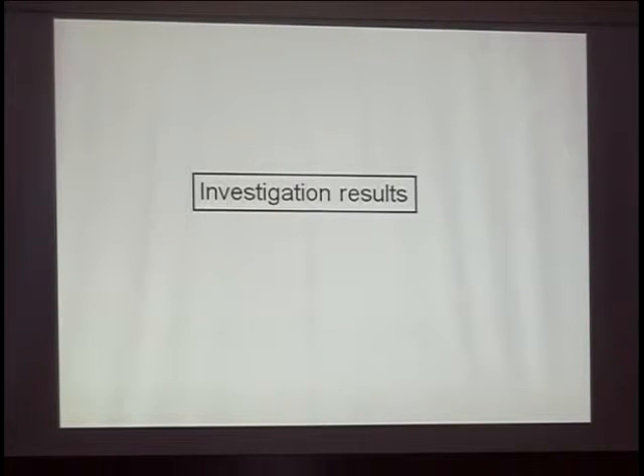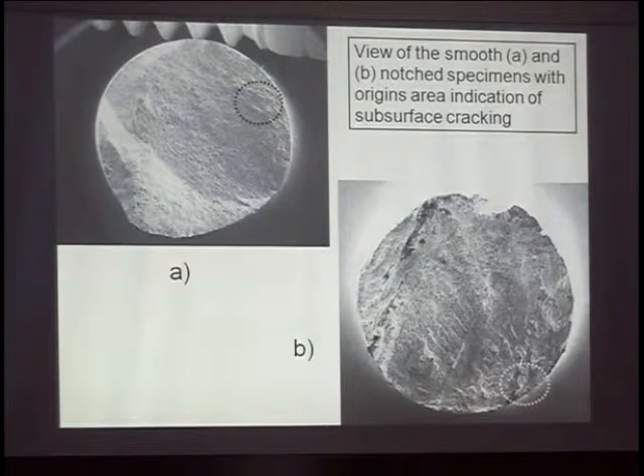Also one of the examples. Fracture surface, because it's very interesting to compare, for instance, smooth specimens or notched specimens, the area of material cracking. For notched specimens, there was a difference because exactly in the area of bifurcation there were two different kinds of material cracking, surface and subsurface. But for smooth specimens, especially after shot peening, only subsurface cracking was seen.